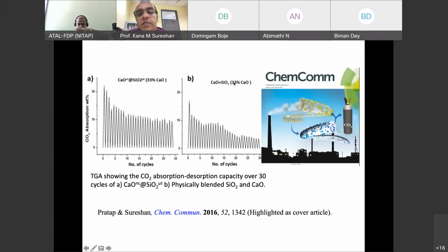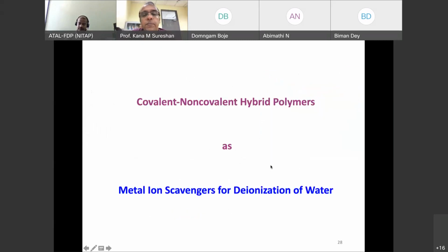If you take the same mixture, 33% calcium oxide and silicon dioxide, and physically mix them without nanocrystals, you see that the initial absorption itself is bad, about 15 to 16 percent. In the next one it goes to 12 percent, and the third it goes to 10 percent. Over 30 cycles it is less than 5%. This is the 5% mark. So there is an effect of this nanocrystallization, and we have shown this in this particular paper.